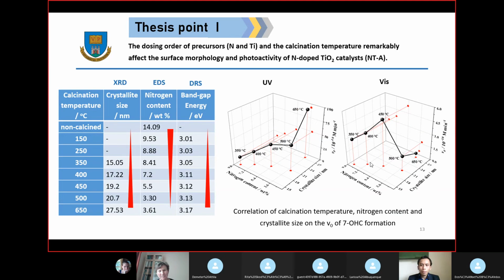However, if we look under visible illumination, besides that, the nitrogen content should be maintained in the catalyst, because it affects the band gap energy and also the efficiency of the light absorption under visible illumination. In this case, we got the optimum condition at 450 degrees Celsius. From this point of view, both crystallite size and the nitrogen content played a crucial role in the photocatalytic activity of nitrogen doped titanium dioxide.